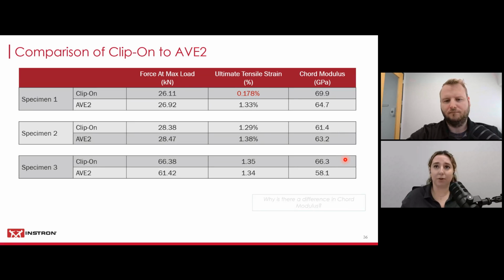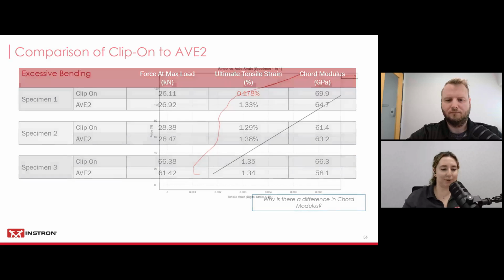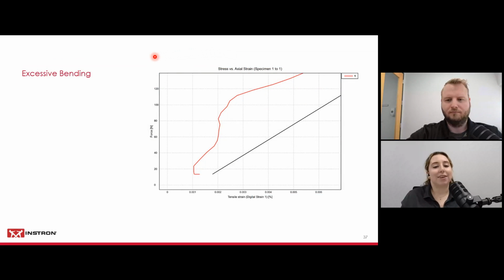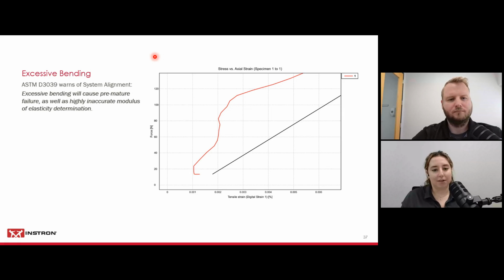And Stefan, if you click real quick, why is there such a difference in my chord modulus? And I'll explain why. I didn't bring this up at the beginning, but ASTM D3039 warns of system alignment. Any kind of excessive bending will cause premature failure, as well as highly inaccurate modulus of elasticity determinations. When I tested my specimens, I set my preload to only 10 newtons, and they broke at 26,000 newtons and 66,000 newtons. This preload was insufficient, which meant that I had some kind of bending in my specimen, and that my excess z-axis was affecting my AVE2 reading.